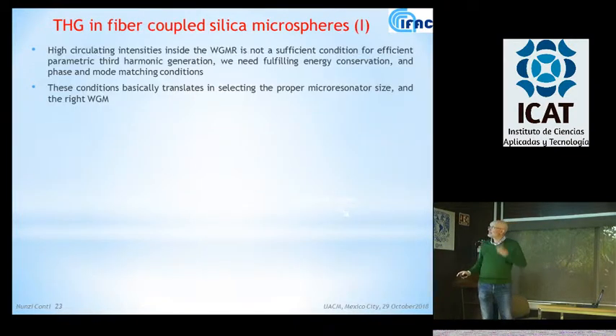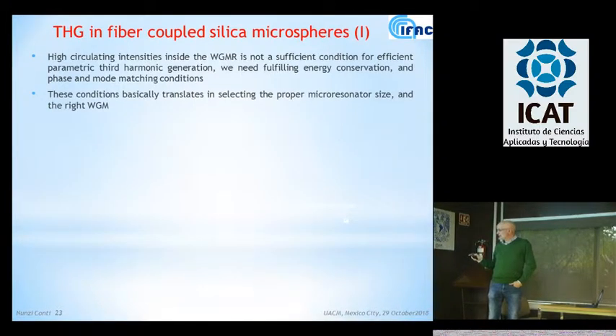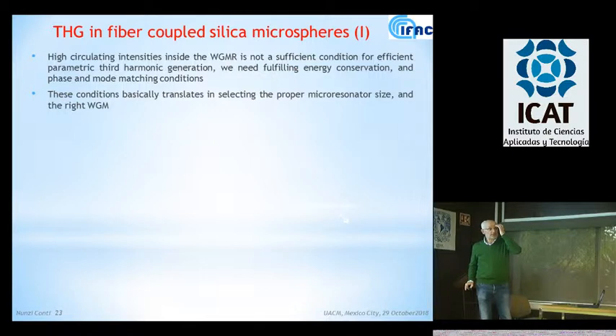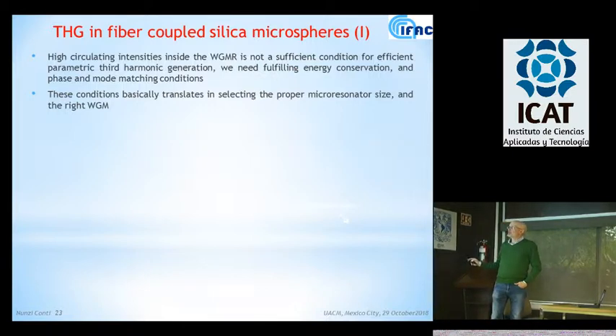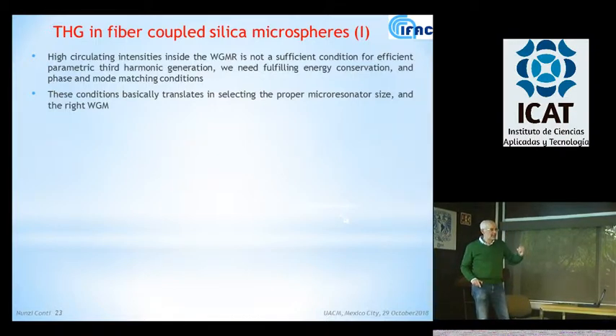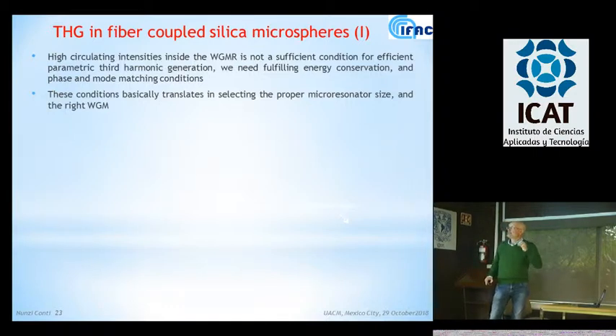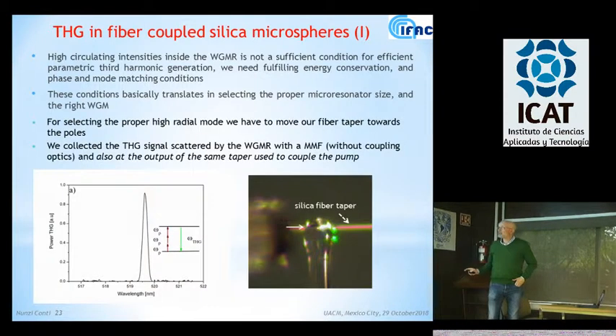So where we applied this, for instance, one we did to generate the third harmonic in a silica microsphere. Of course, you know that having high circulating intensity inside a whispering gallery mode resonator is not a sufficient condition to have a type of parametric third order conversion, because we need to fulfill energy conservation, phase, and mode matching conditions. This basically translates into selecting a certain size for the cavity when you want to have the energy conservation and the right whispering gallery mode to have phase and mode matching. And what we did,